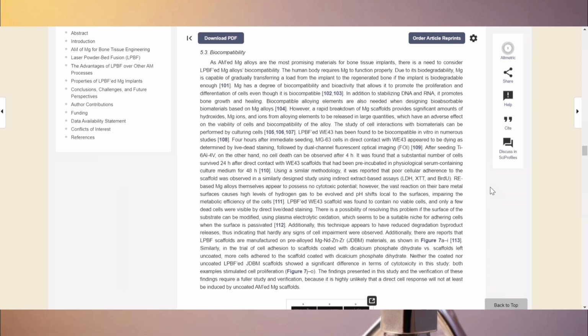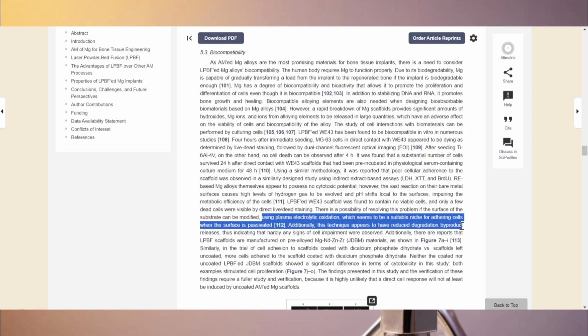Cytotoxicity assessments of rare earth-based magnesium alloys indicate that while these materials do not inherently possess toxic properties, their high degradation rate leads to localized pH shifts and hydrogen gas evolution, which impair cellular metabolism. It is noteworthy that plasma electrolytic oxidation has been identified as a promising surface treatment to enhance cellular adherence and reduce adverse degradation effects, so it can improve scaffold biocompatibility.